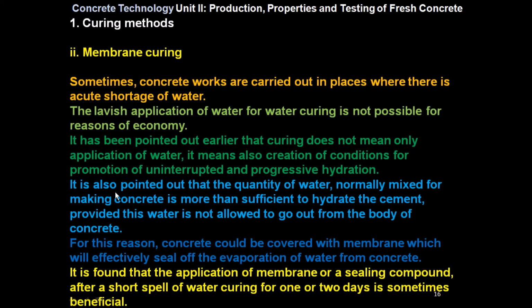It is also pointed out that the quantity of water normally mixed for making concrete is more than sufficient to hydrate the cement, provided this water is not allowed to go out from the body of the concrete. For this reason, concrete could be covered with a membrane which will effectively seal off the evaporation of water from concrete. It is found that the application of a membrane or a sealing compound after a short spell of water curing for 1 or 2 days is sometimes beneficial.